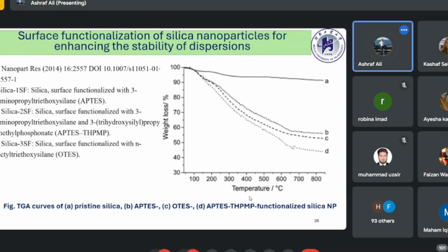Now material A is just a simple silica particle with no modification or surface functionalization. Look at the TGA curve of this bare silica particle. You can see that even after heating to 800 degrees C, the weight of this material is more than 95%. So only 5% weight loss has taken place, and this 5% is due to the removal of adsorbed water, because silica is a hygroscopic substance and it absorbs some water. After heating to 800 degrees C, the water molecules have been removed, and the weight loss is only 5%.